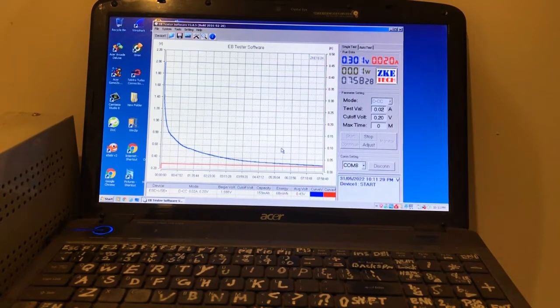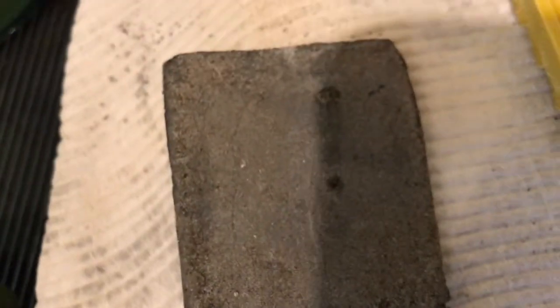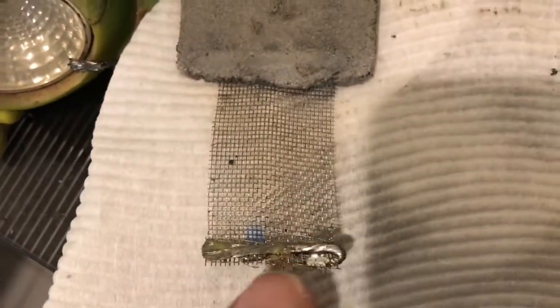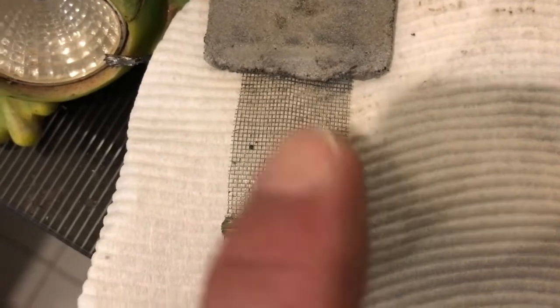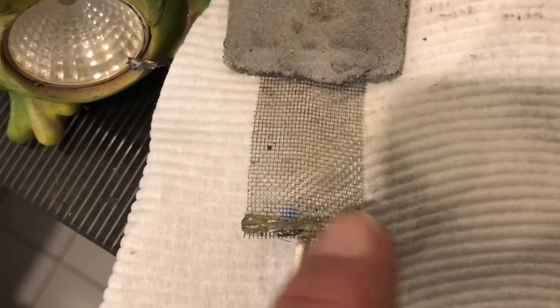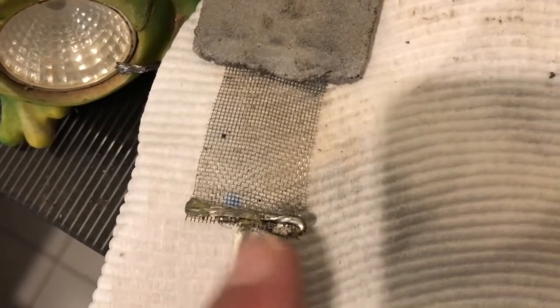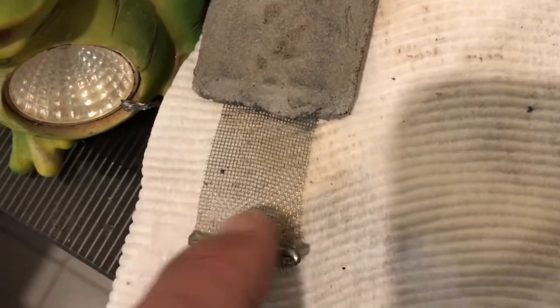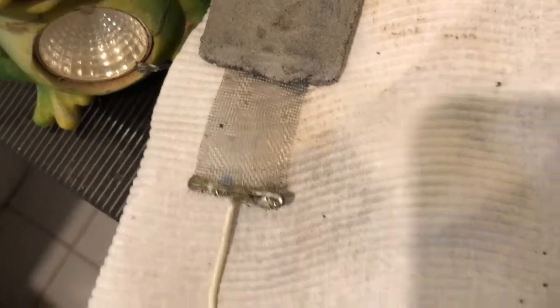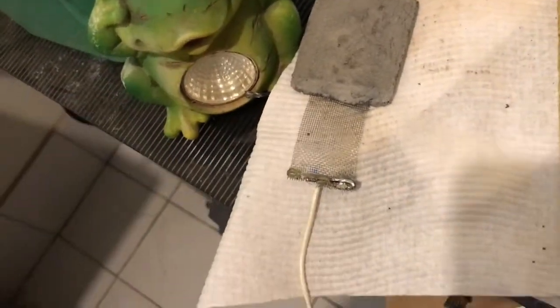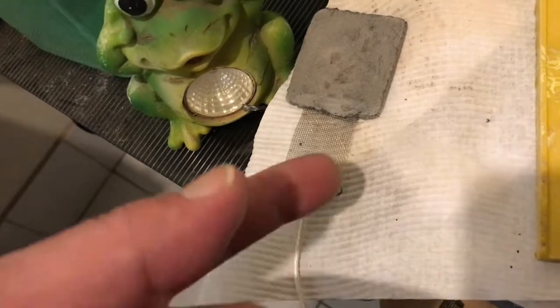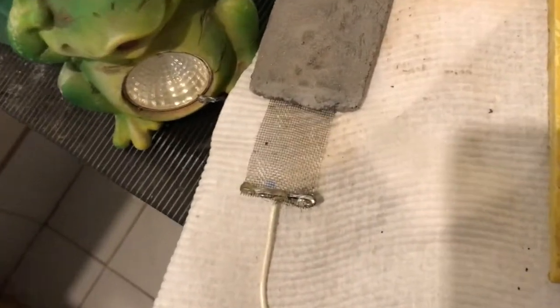So there's something odd that's running with the zinc plate. The other one's there. It seems to be intact still. Not sure if it's galvanic corrosion under the solder and the stainless wire, maybe. But connecting the lead to here, no difference. I've had an alligator clip here with the wire connected also to here, and still not so good.